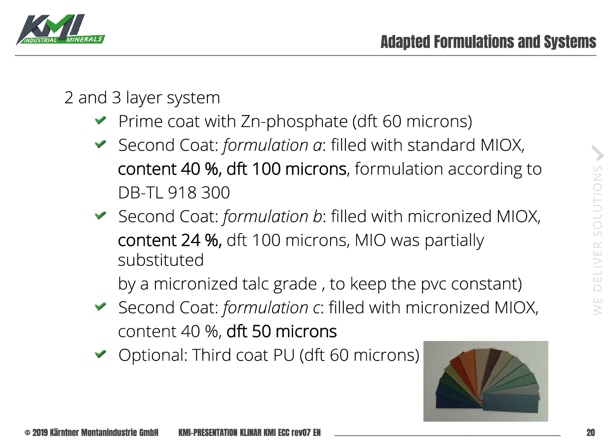And optionally, we tested a third coat, which was a typical polyurethane top coat with again a dry film thickness of 60 microns.